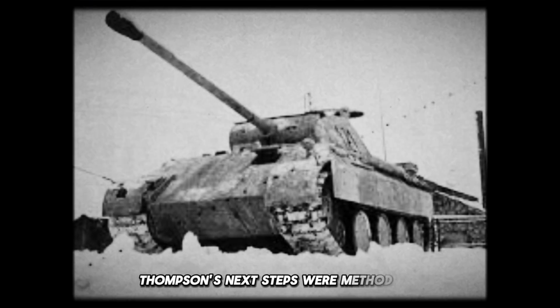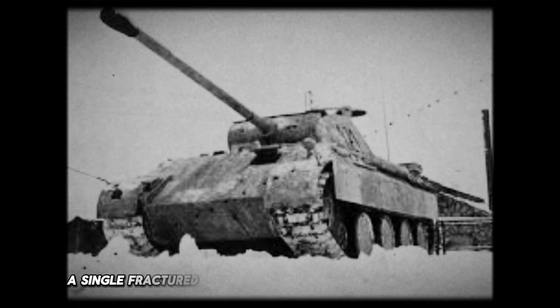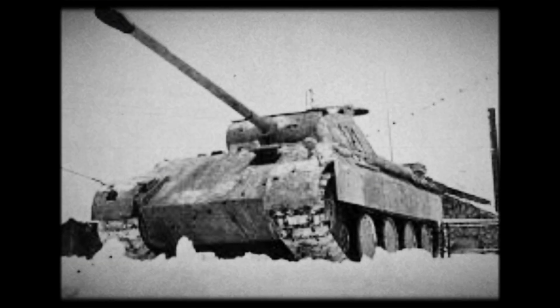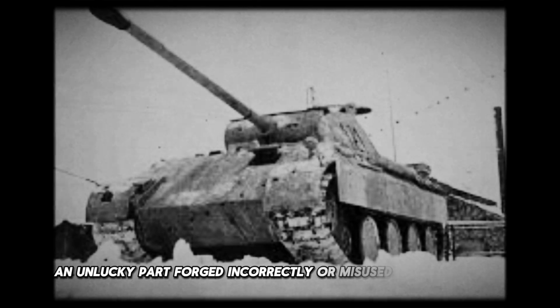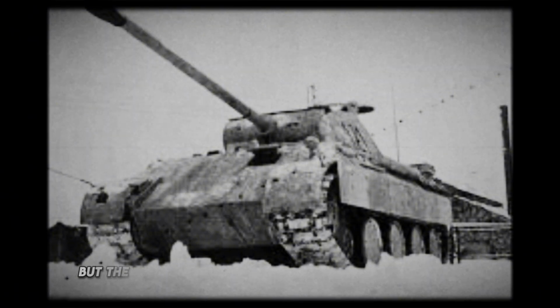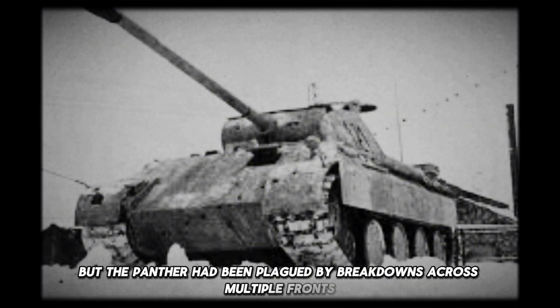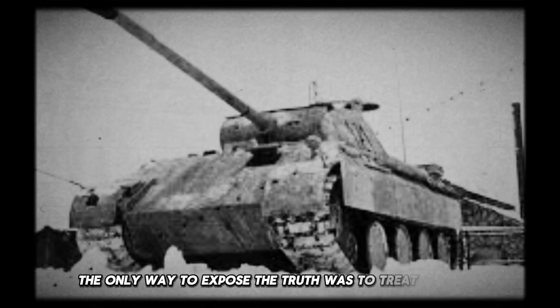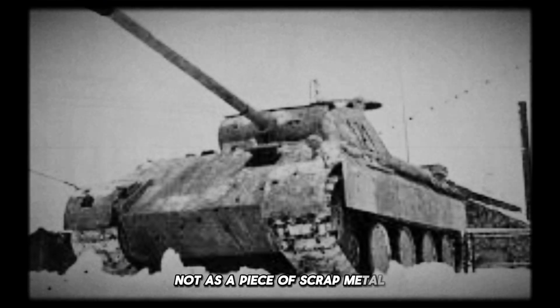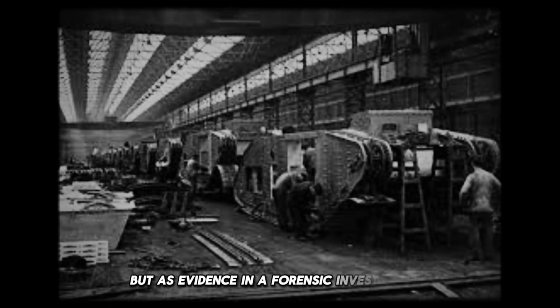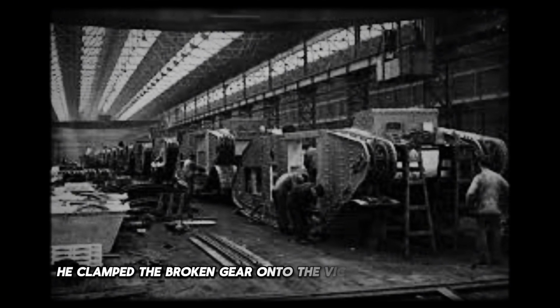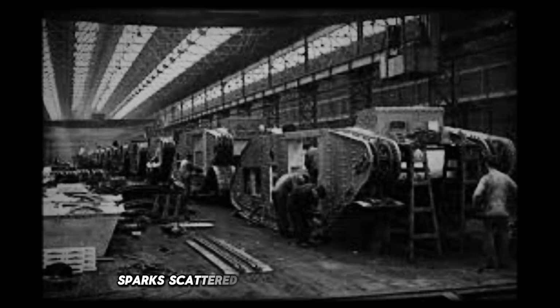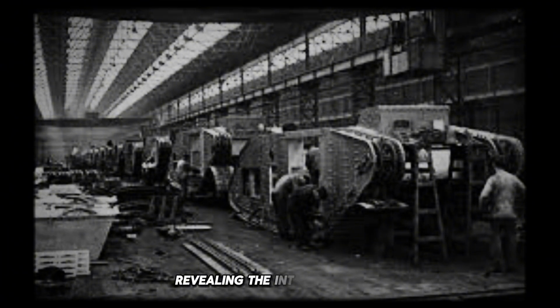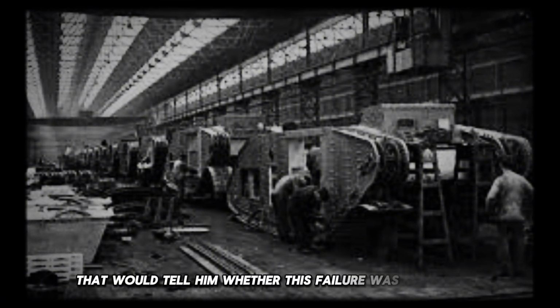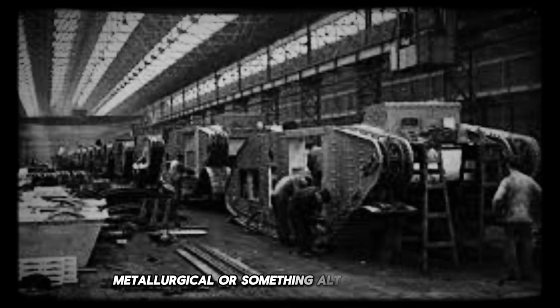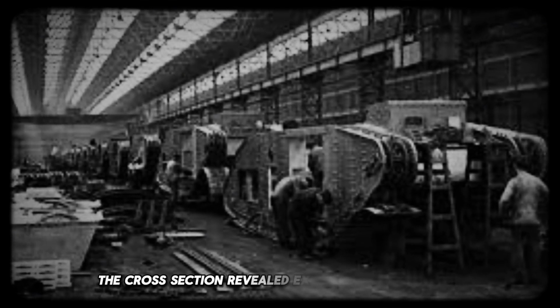Thompson's next steps were methodical, almost surgical. A single fractured gear could be dismissed as a rare failure, an unlucky part forged incorrectly or misused in the chaos of war. But the Panther had been plagued by breakdowns across multiple fronts. The only way to expose the truth was to treat the gear not as a piece of scrap metal, but as evidence in a forensic investigation. He clamped the broken gear onto the vise and began cutting it open. Sparks scattered across the workshop floor, revealing the internal layers that would tell him whether this failure was mechanical, metallurgical, or something altogether worse. The cross-section revealed exactly what he feared.